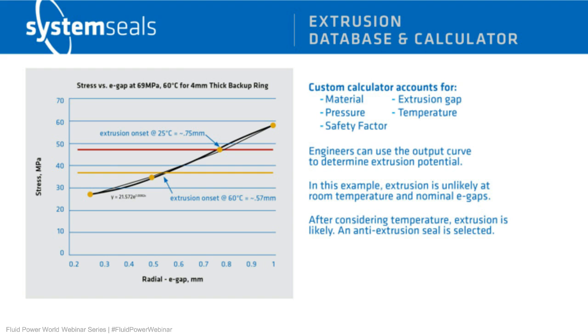I'm sorry, now that's at 25 degrees Celsius. If that material or the application heats up to 60 degrees Celsius, that limit is derated according to the material properties. So we know that material properties change as a function of temperature. We use a DMA in our laboratory, a dynamic mechanical analyzer, in order to determine how to derate these materials as a function of temperature.